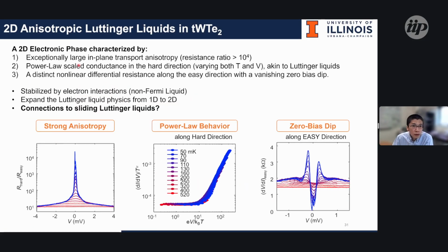So to give you a quick summary: we observe two-dimensional anisotropic Luttinger liquid behavior, or a two-dimensional electronic phase, and it can be captured by observing a nonlinear differential resistance along the easy direction with a vanishing zero-bias dip. This is a strong correlation which we see in such 2D anisotropic systems. And is there any connection to the earlier theoretical proposal of sliding Luttinger liquids?